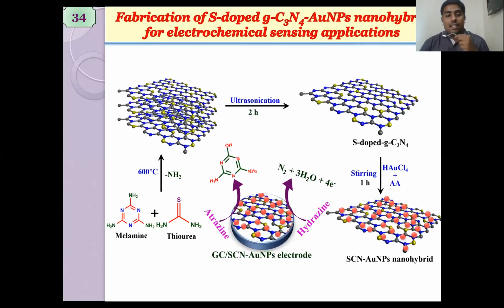The next case is the fabrication of gold nanoparticles on the sulfur doped graphitic carbon nitride, and their composite fabrication on the GC electrode for the sensing of atrazine and hydrazine. As we discussed already, the graphitic carbon nitride is synthesized from melamine. As I want to dope sulfur, I take thiourea as a source for sulfur, and after polycondensation, it forms multi-layers of graphitic carbon nitride.